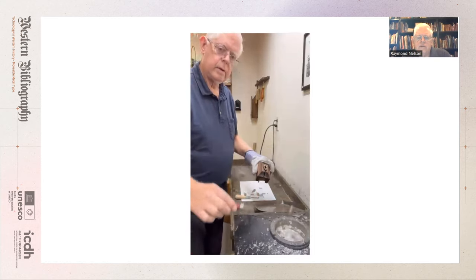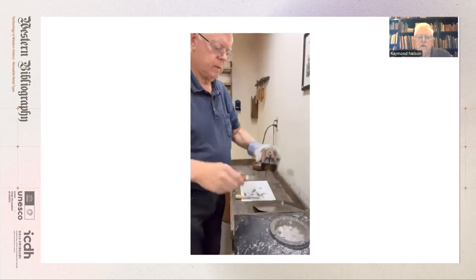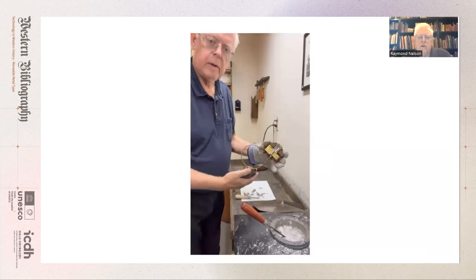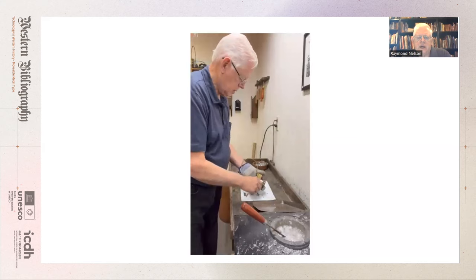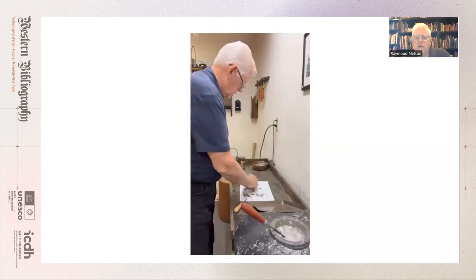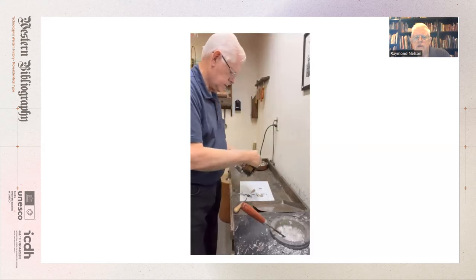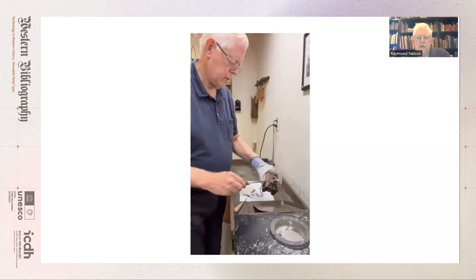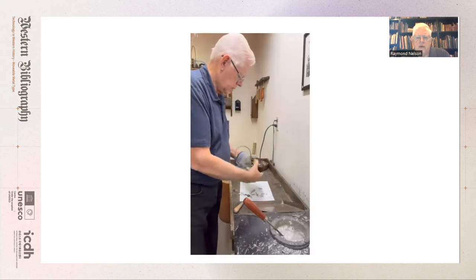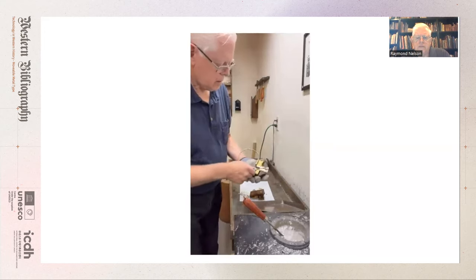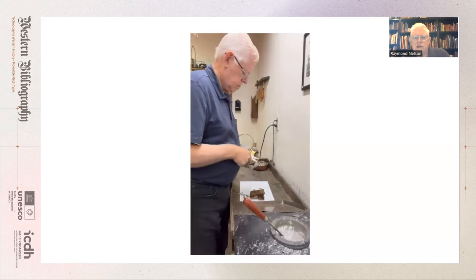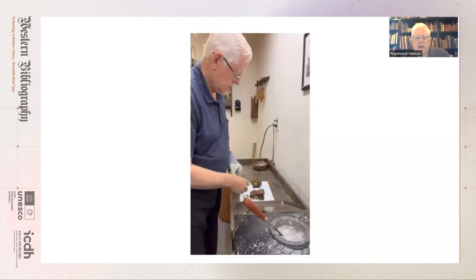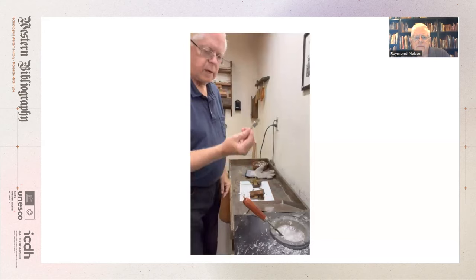In this video, the metal is being stirred — it is totally fluid because it's been heated to about 620 degrees Fahrenheit. Pouring it in with a lift, the lifting motion is necessary in order to fill the mold perfectly. A high percentage of castings are not good. In this style of mold, the jet doesn't want to free from the mold easily, so that's one reason why it's not a good design, though they still used it for quite a long time. The metal is a mixture of lead, tin, and antimony. In early mixtures, they were heavy on the tin and did not have a lot of antimony — early types that have been analyzed suggest that's true. If it's a bad casting, you throw it back in the pot.